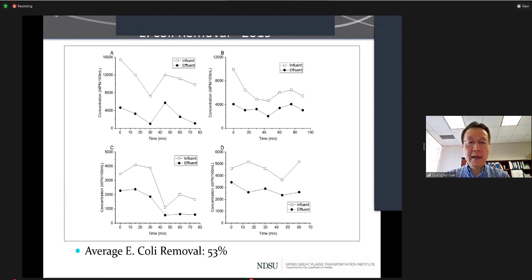Similarly, in 2019, we also evaluated 4 storm events, and the average E. coli removal was 53%. And also one thing I want to point out here that we found in this detention pond, the influent E. coli concentration varies. For example, in 2019, the influent concentration varied from about 1,000 to over 16,000 per 100 ml. So we found a large amount of E. coli in this detention pond, and we were able to remove about 50% through the filter media.